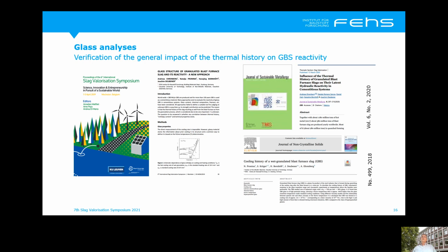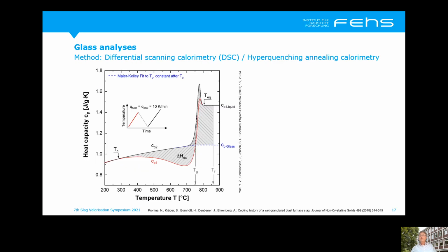The glass analysis, which we use to explain the differences of the properties, was already explained, the principle was explained during the last slag valorization symposium and also in 2 publications in the Journal of Sustainable Metallurgy and in the Journal of Non-Crystalline Solids. Therefore, I do not want to explain too much, but we are able to measure as well the glass transformation temperature Tg, which is measured under standard laboratory conditions, cooling rate, heating rate 10 Kelvin per minute. But we are also able to calculate the so-called fictive temperature, that is a glass transformation temperature under real conditions, which you cannot measure directly.